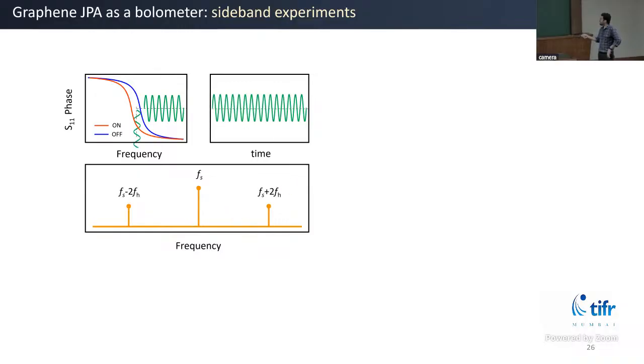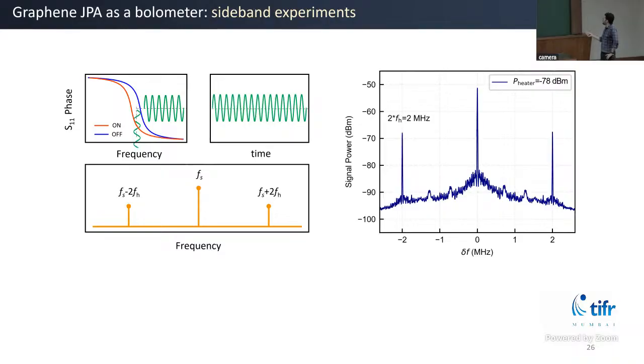If you send the heater current at FH, that will cause Joule heating like I squared R. So that will give you the sideband at Fs plus minus 2 FH, where Fs is the unperturbed resonance frequency of the resonator. And this FH works as a small perturbation around that. Just to give some numbers, this Fs is in gigahertz, for example 5 gigahertz, but this small perturbation is at megahertz. So it's a perturbation on the actual resonance condition. In this experimental data, we use 1 megahertz as our heating signal, and we see the sideband at twice the heater frequency, 2 megahertz.